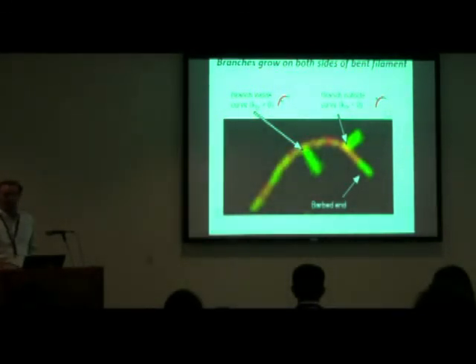Well, our hypothesis is that what's happening at these branched actin networks is that the application of a force is changing the density of the network. And if I nucleate new filaments, if I create new pushing proteins, what I'm doing is spreading the load over more force-generating polymers, and I'm able to handle a greater load. So that's the idea, that as I increase load at the edge of this growing network, I'm actually nucleating new filaments. Okay, so we've recently seen through a range of experiments that the curvature of the filament affects the branching behavior, and this curvature leads us to believe that when these networks are under load, they're more likely to branch on a surface that generates a new filament towards that surface.